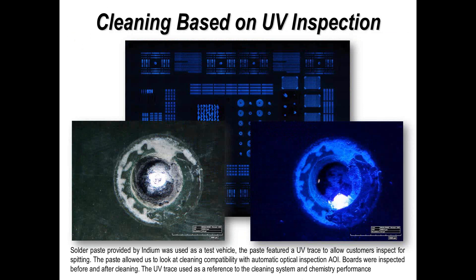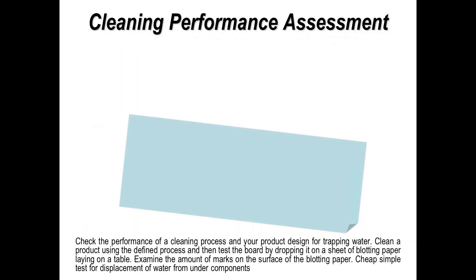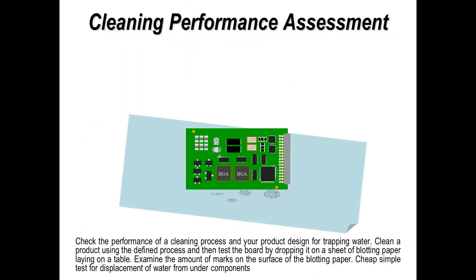A close-up of the same board shows residues after cleaning — not very well cleaned, it may be said — under UV light to show exactly the same thing. Not necessarily associated with cleaning per se, but cleaning and drying: I was amazed when I first saw this technique. Engineers were interested in how much moisture or water droplets are trapped underneath components after a cleaning cycle. They took blotting paper, put it on a bench at the end of the cleaning process, took their boards and banged them onto the surface. Any water and water droplets coming out from underneath components would show on the blotting paper.